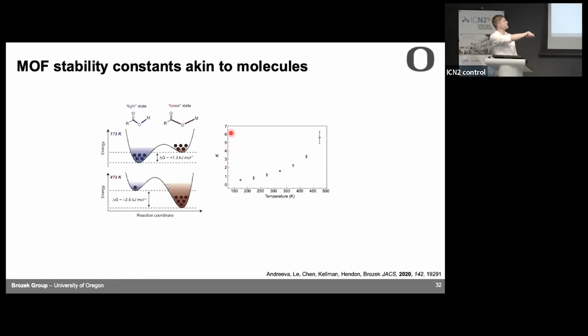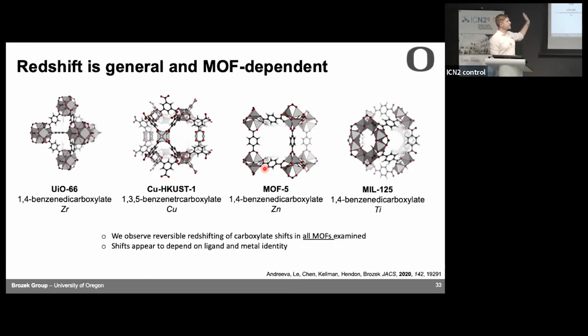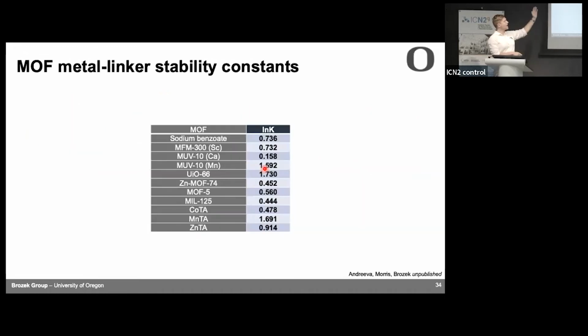And so here, this is the equilibrium constant of that metal ligand bond as a function of temperature. And one thing that was nice to see is that the room temperature value, right about here, is spot on. It's totally consistent with the molecular log K values that I told you before. So it's saying that these metal carboxylate bonds are really acting like these dynamic metal carboxylate molecules that people have seen. So like I said, we've done this for all these different common MOFs. They all do the same thing. And with that, at room temperature, I can tell you what that equilibrium constant is.